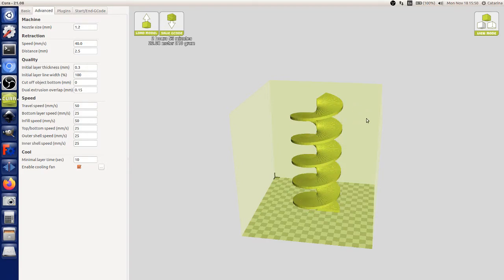Right now with the 0.8 millimeter nozzle, you can see the extruder heater has a light on the control, and you can see when the extruder is on, it blinks for the duty cycle of how much it's on and how much it's off. Right now we're seeing a duty cycle of about 80-90%. What does that mean? We're printing at 50 millimeters per second, so if we try to push the limits to either a larger nozzle, which prints out more material, or a faster print speed, you're not going to be able to do it without reducing the temperature, so it actually fails. If we can print well at a 0.8 millimeter nozzle with about 90% duty cycle, you only have a little bit of wiggle room for how fast you can go.